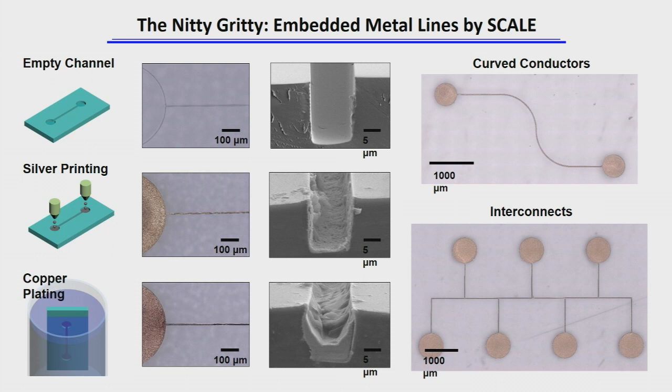The first thing you need for circuits is metal lines. They're also called interconnects. So how would we print metal lines? These are copper metal lines printed by the SCALE process, roll-to-roll. Well, first we might imprint features that look like this, a reservoir and a channel, and we deliver ink to the reservoirs. Capillarity draws the ink into the channel, and when the ink dries, we now have a silver lining on this trench. Now, we want a solid metal line, and the way we do this is by plating copper. So we immerse it in a copper plating solution, and we build up bulk copper, which is what gives you these lines. And they have very low resistance, and so we can make metal lines. And this is just a few microns here. And the aspect ratio is about one-to-one, so we can make nice metal lines this way.